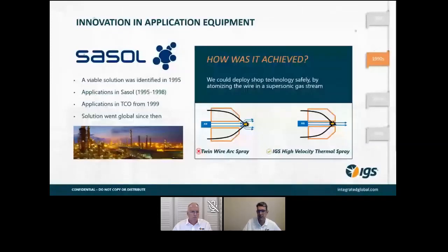And what that in essence did is it reduced the particle sizes that are sprayed with a system like this by an order of magnitude. So it moved the particle sizes from 50 to 300 microns at times down to the 5 to 50 micron size range. So the system produced very small particles. They became very flat when they were sprayed because of the high velocity involved in atomizing them. And the quality of the coatings was much higher. So that allowed application of the technology in more critical environments where more noble coatings, such as Inconel, Hastelloy types of materials, nickel chrome types of materials were really needed for that process.